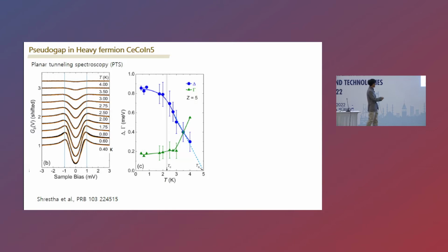So when they plotted the gap size as a function of temperature, they found that the 0.8 millielectron volt gap size is suppressed with increasing temperature as expected. However, at around Tc, it does not go to 0 as expected, but rather has a finite value. It is then gradually suppressed and extrapolates to 0 at around 5 Kelvin, which they assign as a pseudogap temperature. They use this gradual crossover as evidence for preformed Cooper pairs as an origin of a pseudogap.